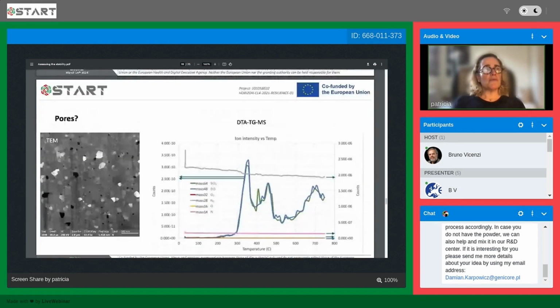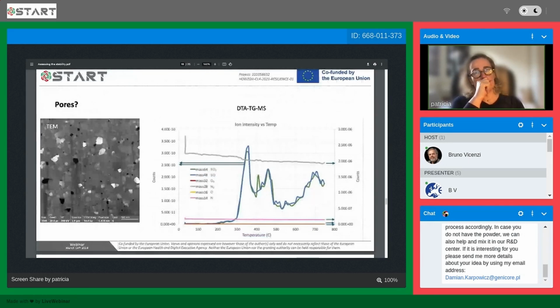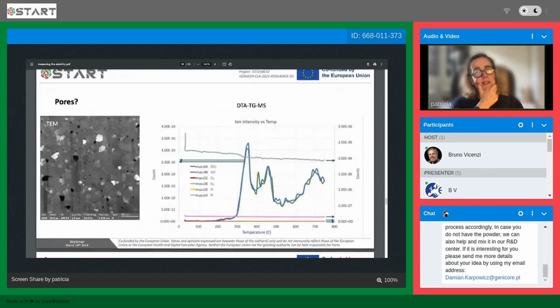Then the other question was, what is this type of pores? What is this porosity? So at SINTEF, we have this DTA TG mass spectrometry instrument. So we just do a DTA and we measure the mass as well by TG, but then we have the possibility to measure the composition of the gases which are being released by the sample. And then what we could conclude from this is that we are losing oxygen, we are losing sulfur from our tetrahedrite. And this means that SO2 is being formed. So you see that we have the mass for the SO2 and SO. After annealing at around 300, this starts to happen.